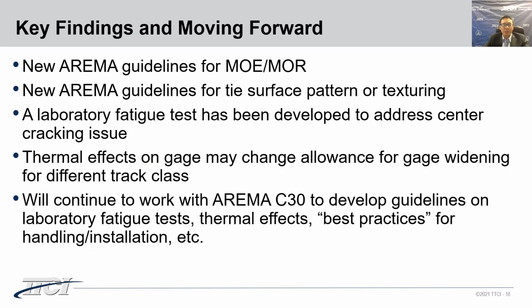To summarize my presentation, here are some key findings from the composite tie research, including new guidelines for MOE and MOR based on field tests and observations. We also implemented new AREMA guidelines for a tie surface pattern to ensure the tie lateral stability. In addition, we developed a fatigue test to address the center cracking issue, and we also found that the thermal effects on gauge may change the FRA allowance for gauge widening. We will continue to work with the AREMA Committee 30 on topics including laboratory fatigue tests and thermal effects to improve the in-track performance of composite ties.